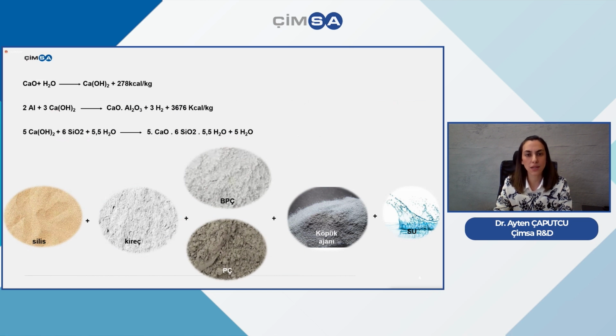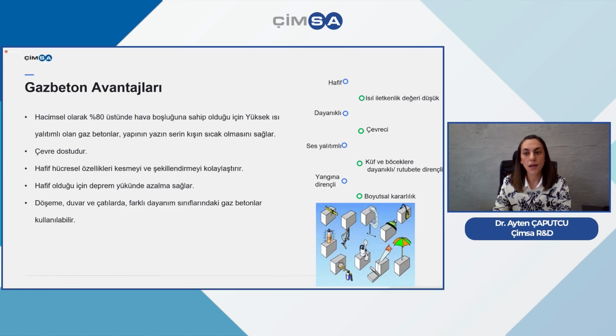And of course, in order to have the foaming effect, there is a foaming agent which we have used, and at approximately 210 degrees Celsius they are being cured. As a reaction of the materials with each other, and with the reaction of lime in connection with water, we have an aluminium reaction, and calcium aluminum oxidation is taking place, and with silicium it creates calcium hydro silicate oxides, and you see the discharge here.